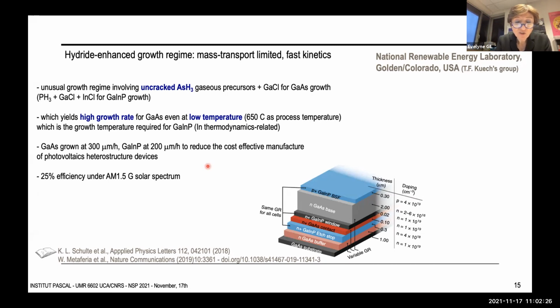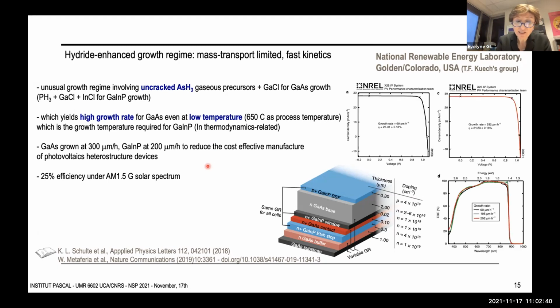Of course, when it comes to very high growth rate, an issue is the incorporation of defects, and especially deep level defects, and namely the arsenic antisite defect, usually known as EL2. And Kuech's group demonstrated that performance of the devices was not affected, even when the heterostructure is grown at some 300 microns per hour.